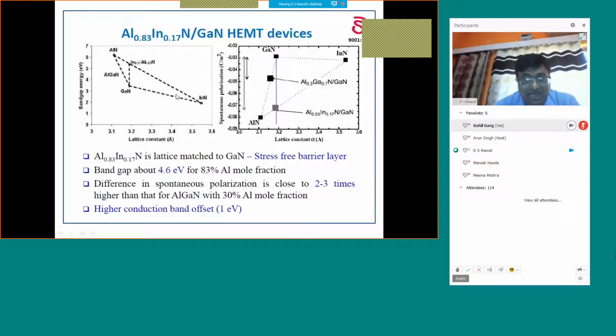Similarly, if we use aluminium nitride in thin layers, the spontaneous polarization difference is even more. If we grow a very thin aluminium nitride layer over gallium nitride, there may be slight strain, but because of the very high difference in spontaneous polarization, we get very high current density devices. So these new generation devices are now being reported worldwide based on these two kinds of heterostructures, and people are going for aluminium indium nitride or aluminium nitride devices.